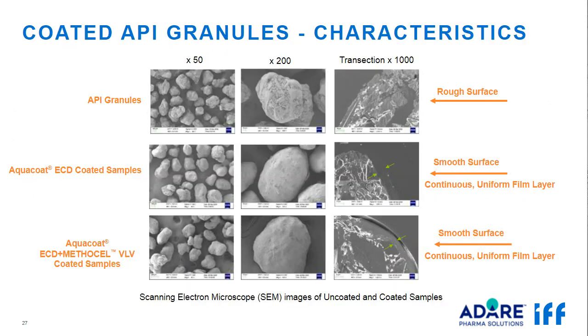These are SEM images of uncoated and coated samples. Uncoated samples on the top have rough surfaces which were nicely covered with a continuous and uniform film of ethylcellulose. Coated granules without pore-formers are shown in the middle row and with the pore-former shown at the bottom. Both have smooth surfaces as shown in these images.